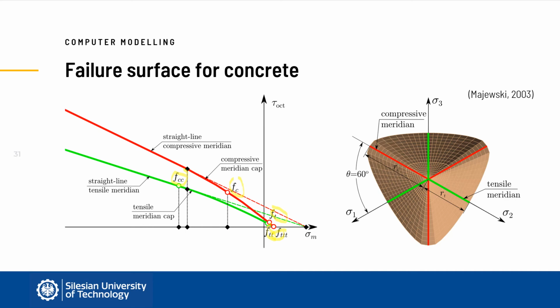It is also known that the meridians of the failure surface are not straight lines because the deviatoric section becomes closer to circular in the zone of tensile stresses. The criteria are represented by introduction of the cap in that area or by describing the meridians as smooth, curved lines. Moreover, the deviatoric section of the surface is not circular and it is not a solid of revolution. If the applied material model accounts for plasticity, such as in case of concrete in compression, two surfaces are defined: the failure surface and additionally the yield surface, and they are usually based on the same criterion.